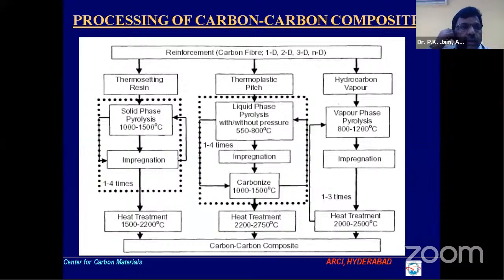Now, a carbon composite is a simple composite. You take the fibers, any one directional, two directional, three directional, any directional reinforcement, and then you take it into the matrix. Matrix can be thermosetting resin, thermoplastic pitch, or hydrocarbon gas, which we popularly call CVD, the chemical vapor deposition. Now this becomes a polymer composite. Now this polymer composite has its limitations. It cannot be used for high temperature application.